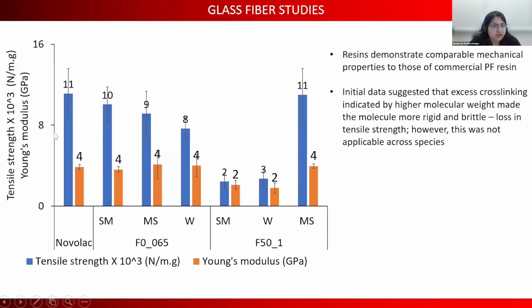As you can see, the initial data showed that many of the lignins, depending upon the furfural content and the pH conditions that they were exposed to, were quite comparable to the commercial Novolac resin. And some of the data also suggested that if there was excessive cross-linking, which meant the molecular weight had gone up, the molecule was rigid. And so if the molecular weight was too high, that didn't necessarily mean that the tensile strength would be high. It would make the resin more brittle, and it would suffer in the mechanical properties.